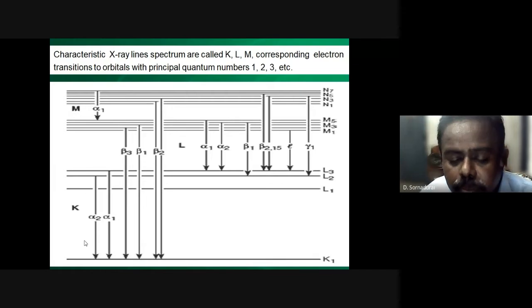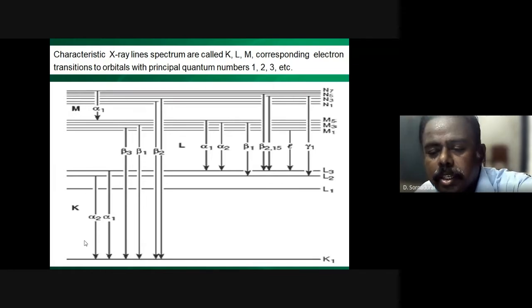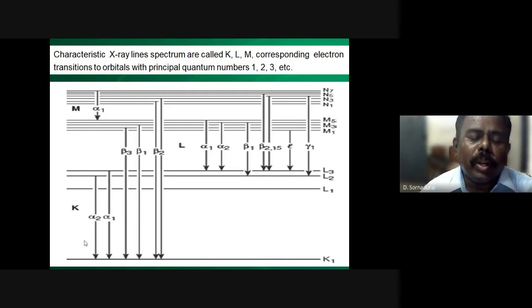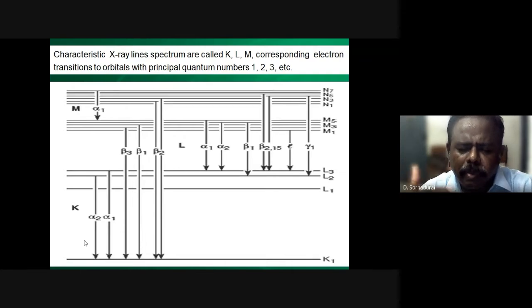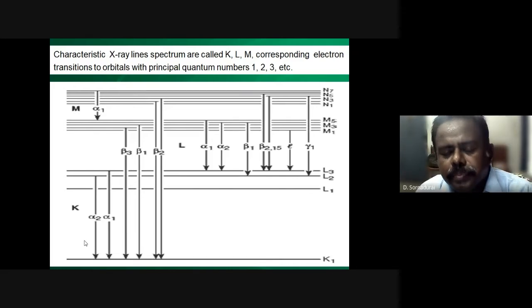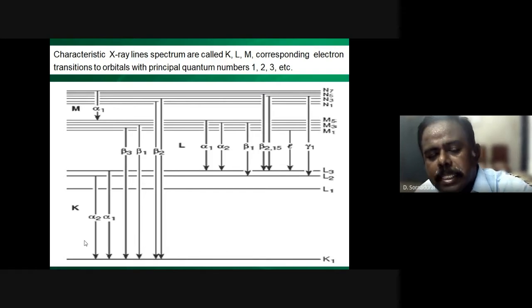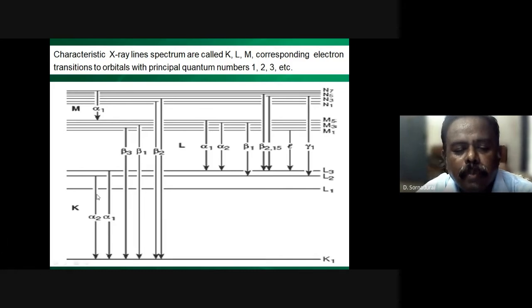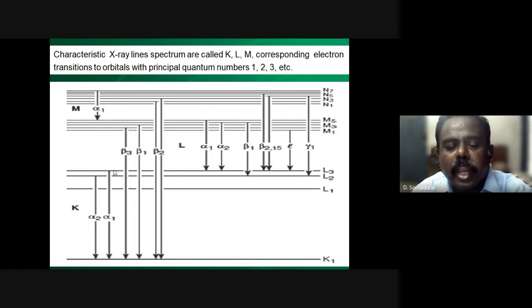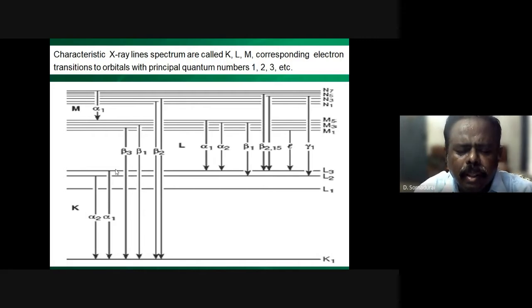The reason behind that is that it is coming from L3, where more orbitals will be there, so more electrons will be coming from that energy level to the K orbit. Similarly, the number of electrons will be less for the K alpha 2. So the ratio between the number of electrons for K alpha 1 and K alpha 2 is exactly half. That is why K alpha 2 will have exactly a 1:2 ratio of the intensity.